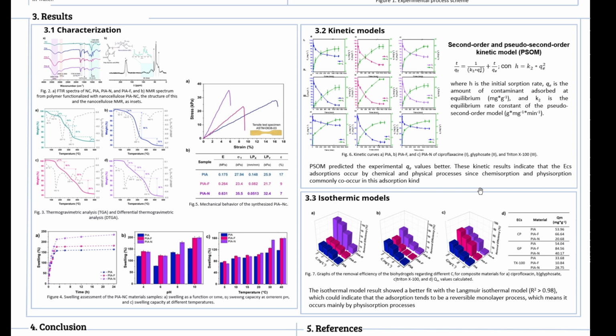Finally, for the evaluation of emerging contaminant removal, the samples were put in contact with a solution of predetermined concentrations of the contaminants. Three emerging contaminants were studied: a non-ionic surfactant, Triton X-100, an antibiotic, ciprofloxacin, and an herbicide, glyphosate. The quantification was made using the UV-Vis technique at the wavelength characteristic of each contaminant. The removal kinetics was determined by measuring the concentration variation of the problem solution at different times, with initial concentrations of 10, 50, and 100 milligrams per liter, varying the pH from 4 to 10 and the temperature from 5 to 40 degrees Celsius.